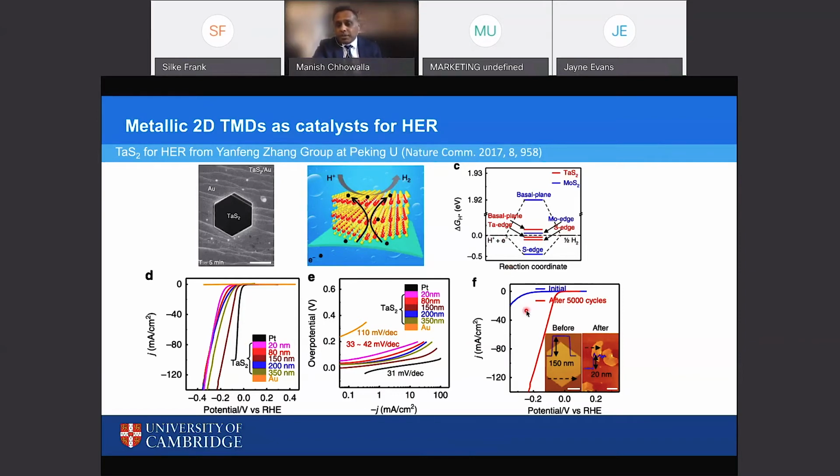And again, Robson mentioned this, but one curious thing about these materials is that they improve with cycling. That is, this is the initial HER performance, but as you cycle up to 5,000 cycles, you can see that both the overpotential and the Tafel slope decrease quite dramatically.